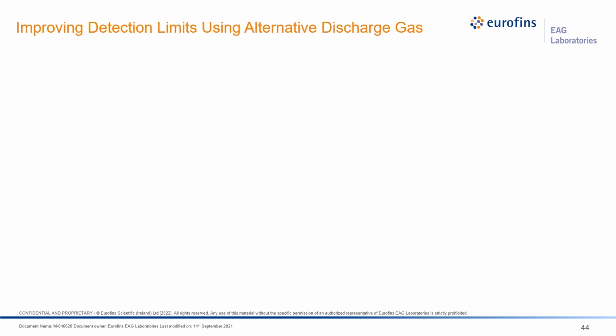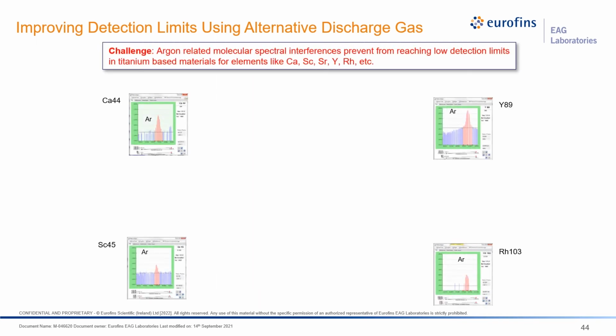However, the ASTM method is not without issues. One of the issues is that it creates argon-related molecular spectral interference for several important elements in titanium-based material, including calcium, scandium, strontium, yttrium, and rhodium. Here you can see that when analyzing isotopes like calcium 44, scandium 45, yttrium 89, and rhodium 103, there is a strong argon interference, and it is not easy to resolve.